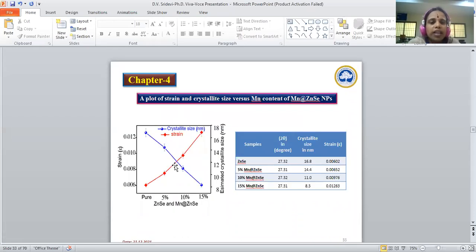This slide shows a plot of strain and crystallite size versus manganese in zinc selenide nanoparticles. The crystallite size of zinc selenide nanoparticles was found to be 16.8 nanometer. By doping manganese into the zinc selenide nanoparticles, the crystallite size was found to decrease from 16.8 to 8.3 nanometer with an increase of strain values, which can be calculated by plotting strain versus crystallite size for the as-synthesized nanoparticles, as shown in this slide.